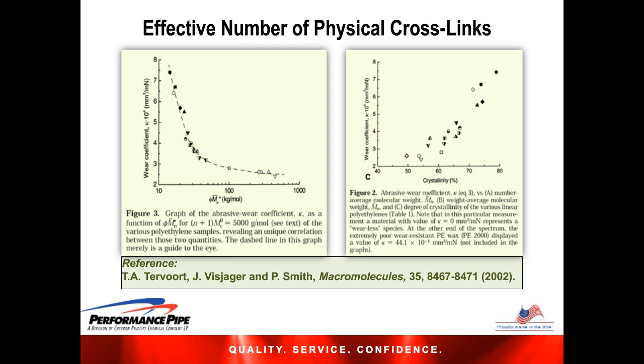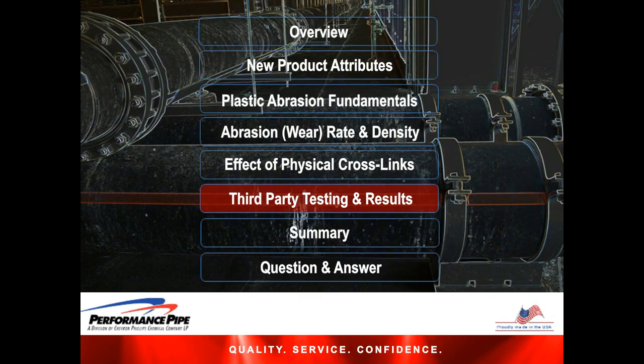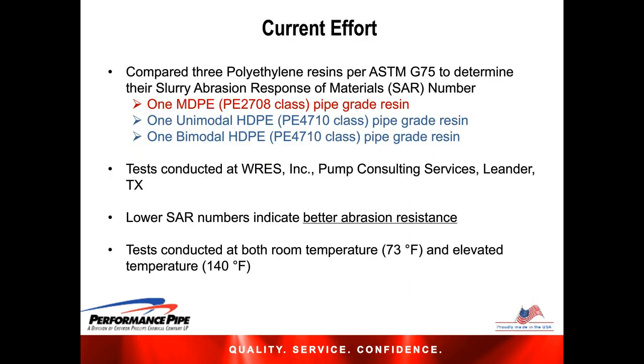So we basically took all of this science and understanding and decided to do a little bit of testing with our own resins to see if these fundamentals held true. To that end, we took three different polyethylene resins within the Chevron Phillips pipe family: the medium density resin that Wes talked about a little while ago, a unimodal high density resin, which was a PE 4710 class pipe grade material, and a bimodal high density PE 4710 class pipe material as well. This was done to give us a good broad range of molecular structures and therefore make the results more relevant.